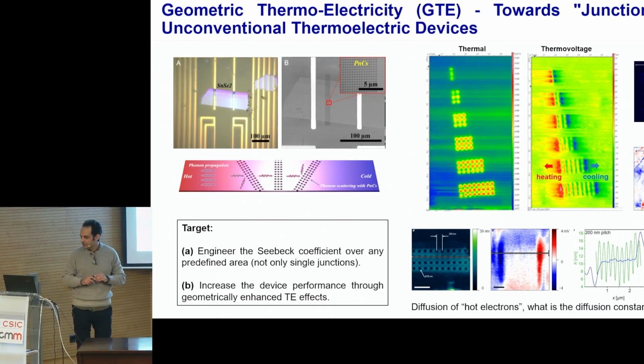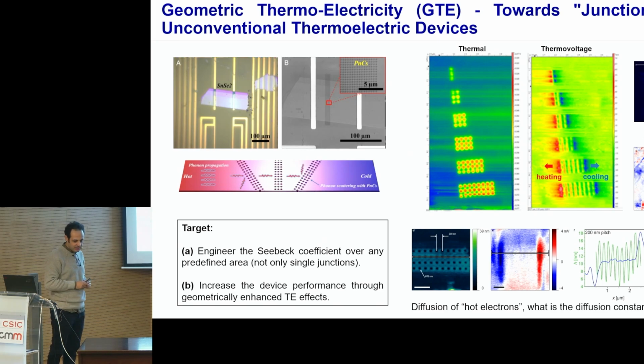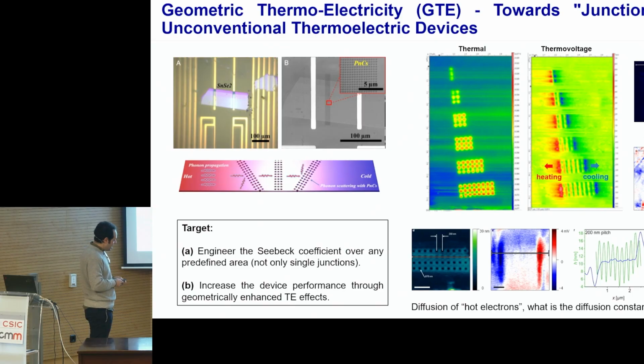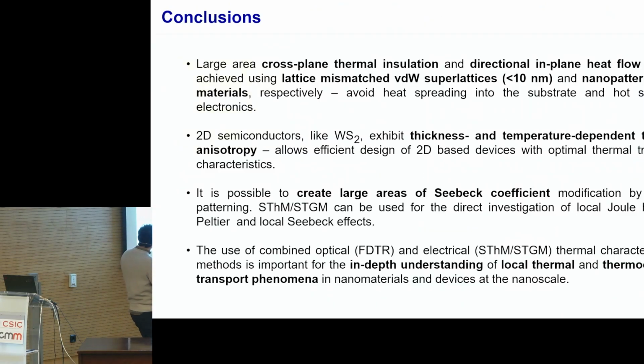I don't want to say more about this, but we also have some calculations to understand these thermovoltage profiles and the Seebeck measurements. And with this, I would like to go to the conclusions. So first, we saw that large area cross-plane thermal insulation and directional in-plane heat flow can be achieved by different methods. We saw the lattice mismatched van der Waals superlattices and the nanopatterned 2D materials, and this is hopefully useful in order to avoid the heat spreading into the substrate and the hotspot formation.